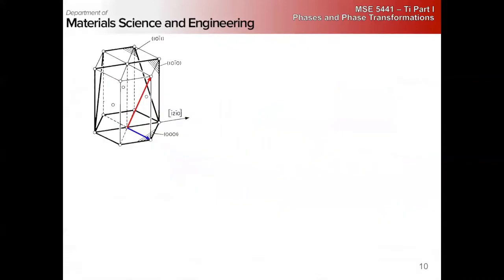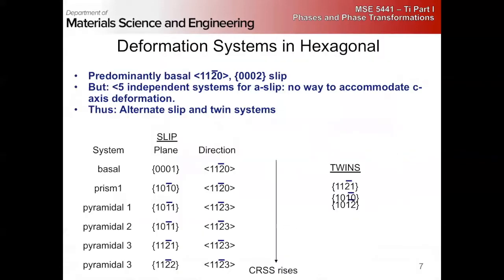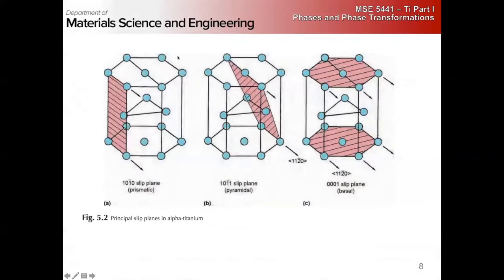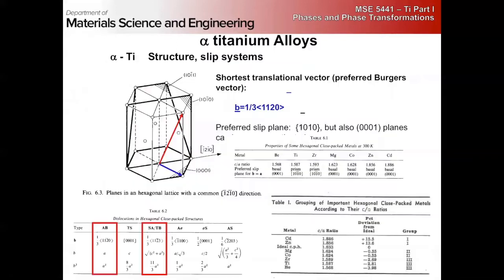All right, so slip directions are, there's also other pyramidal slip systems. So this is going to have a much stronger temperature dependence. So at higher temperatures, this becomes much easier. This isn't going to change too much. So depending on the temperature, we're going to have very different modes, slip modes activated.